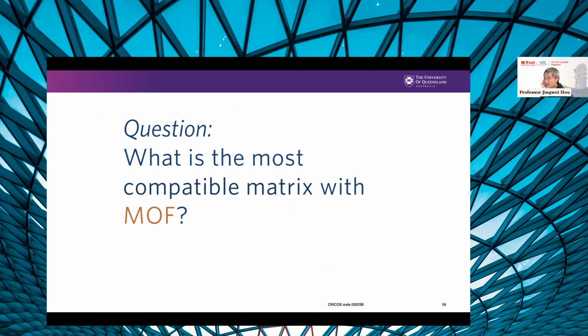That's exactly what we're doing right now. But the challenge is usually COF is highly porous. The pore size is pretty large. You get the interpenetration issue for the COF itself, and also the thermal stability, thermal compatibility issue. But now we can reduce the melting temperature for MOF to around 200 degrees C, which is pretty low from our standpoint. But for the COF people, it's still very nastily high. We're still trying to find somewhere we can meet in between.